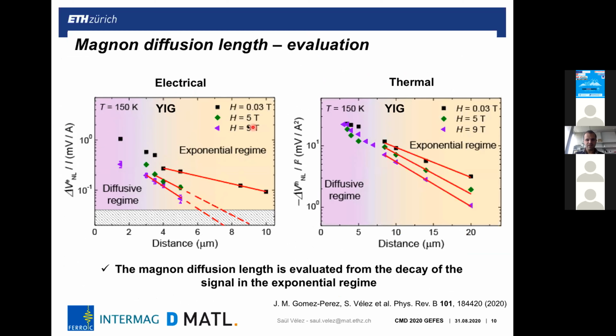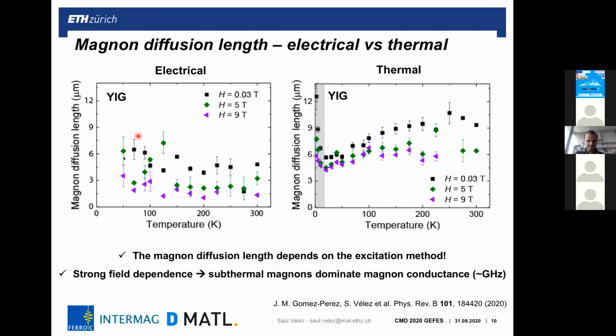And we do so at different magnetic fields and at different temperatures. What we observe is that we have a different magnon diffusion length for electrically excited magnons with respect to the thermal ones. And also we observe a large field dependence. So this together tells us that we excite different magnon distributions when we excite electrically or when we excite thermally. We excite different magnon contributions, and these magnons contribute differently to the magnon transport. And second, because of this strong field dependence, it tells us that there should be a domination: sub-thermal magnons dominate the magnon transport.